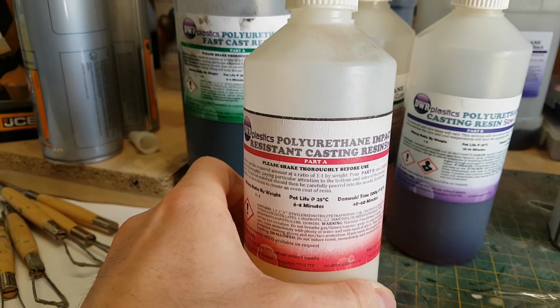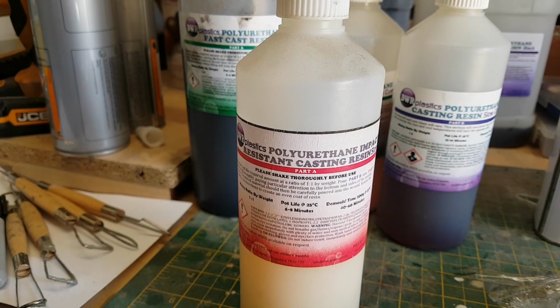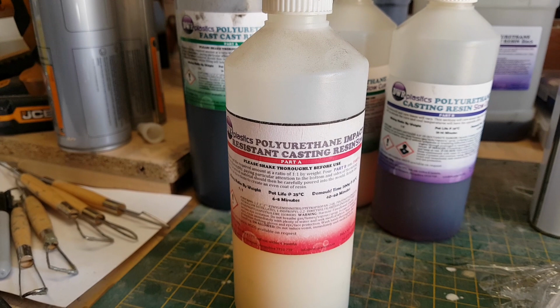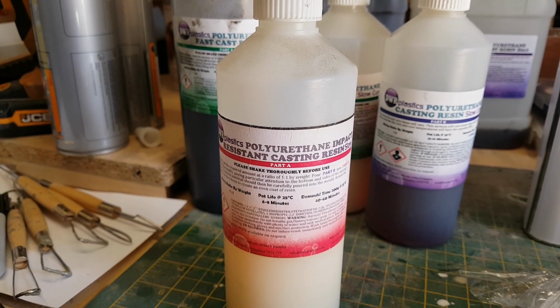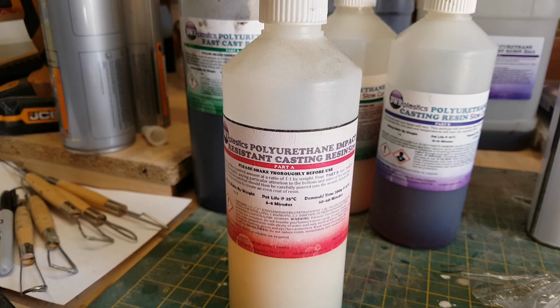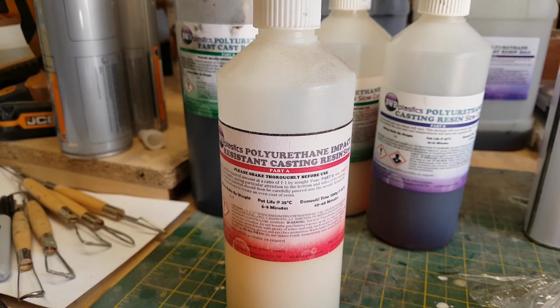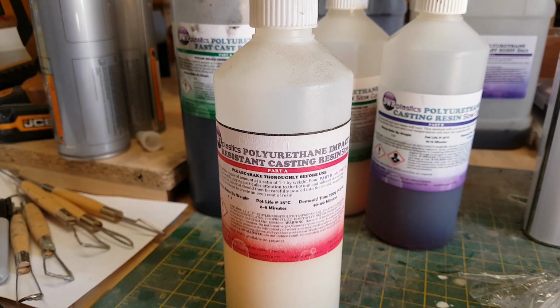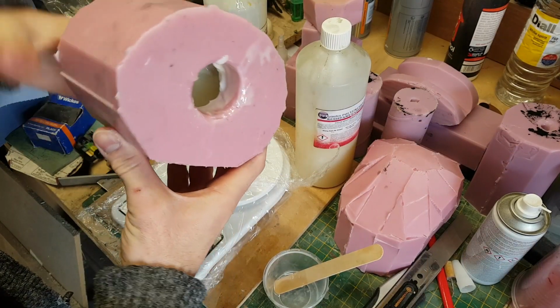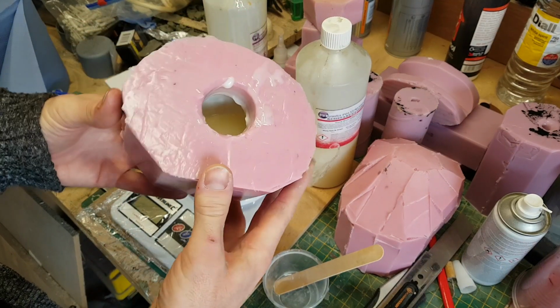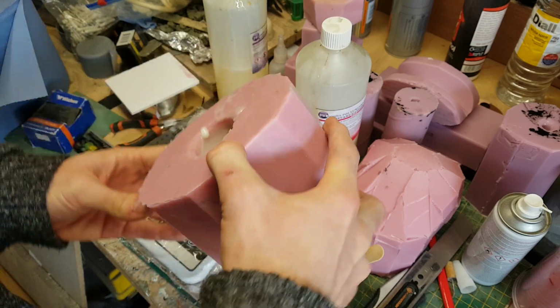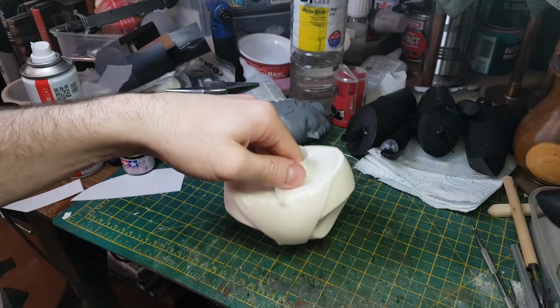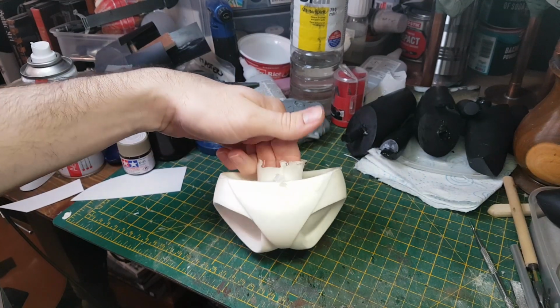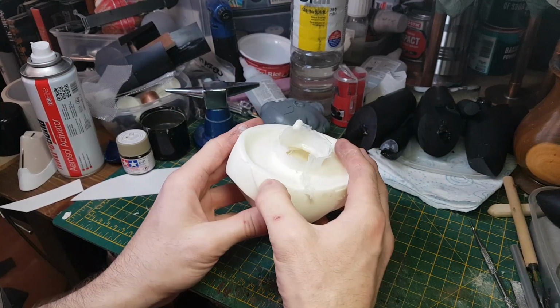The other advantage of this type of resin is it cures in a slightly different way. Polyurethane resins often cure quite quickly, so they'll stay liquid for a time and then they suddenly go hard. This type of resin slowly cures from liquid to solid. What that means is it can be used to rotocast. What that means is you pour a small amount into your mold, then you rotate the mold around, and as the resin cures, it sticks to the outside of the mold and leaves you with a hollow cast. And I use this technique for a sculpture I'm working on at the minute, as you can see here.